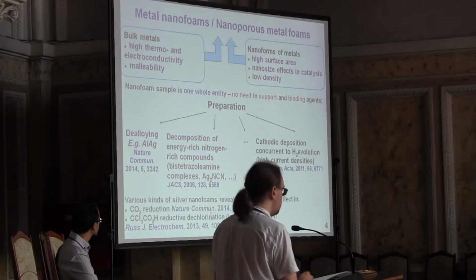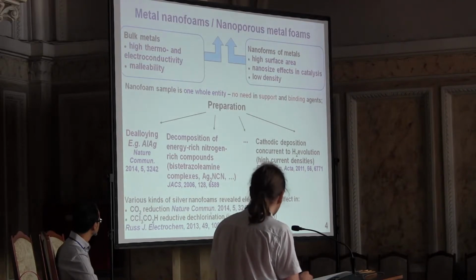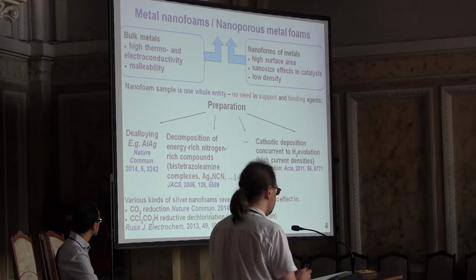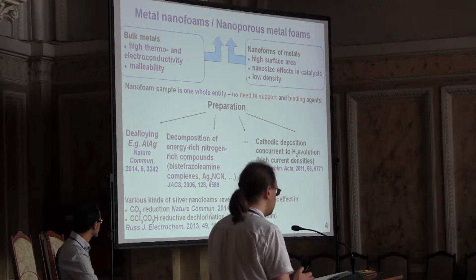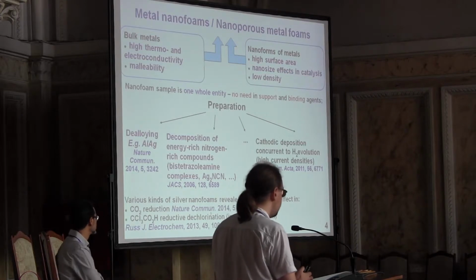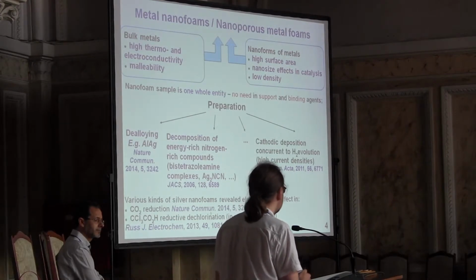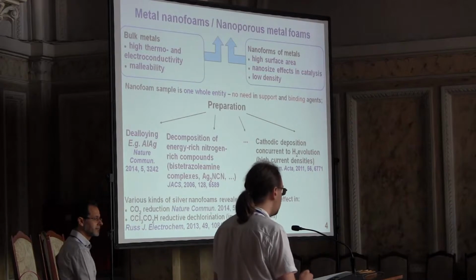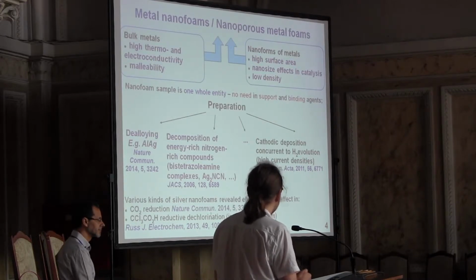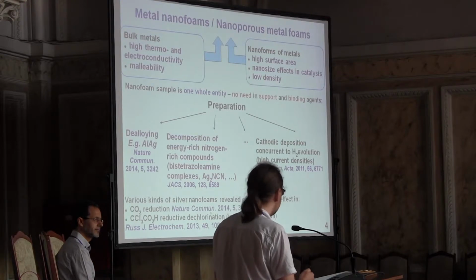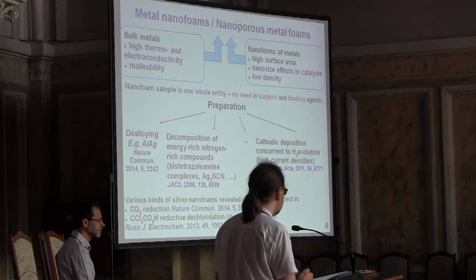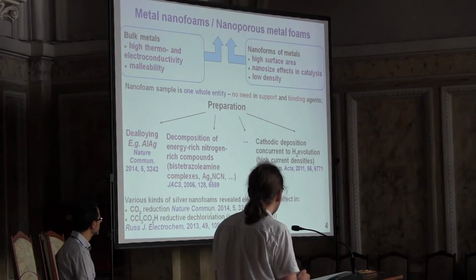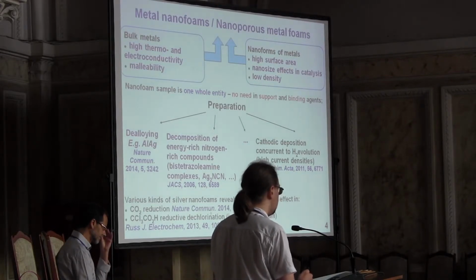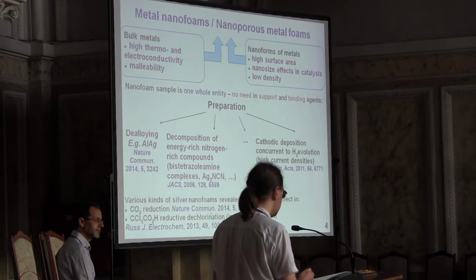First of all, I speak about high electroconductivity. Additionally, it should be noted that nanofoam sample is one whole entity and doesn't require any binding agents or any support in principle, which is especially important if we work in non-aqueous solutions. Nanofoams can be prepared by different ways. The most promising for electrocatalysts is use of cathodic deposition under high current densities, because in such case we can obtain a readily available electrode.